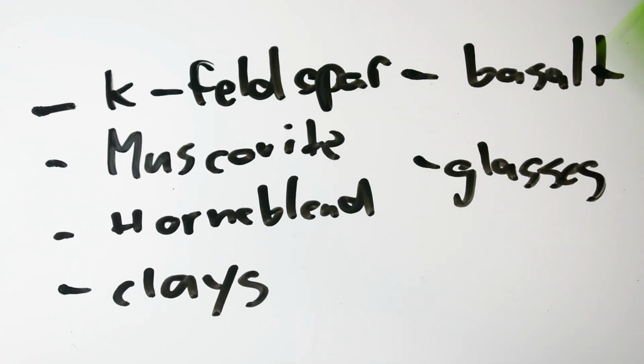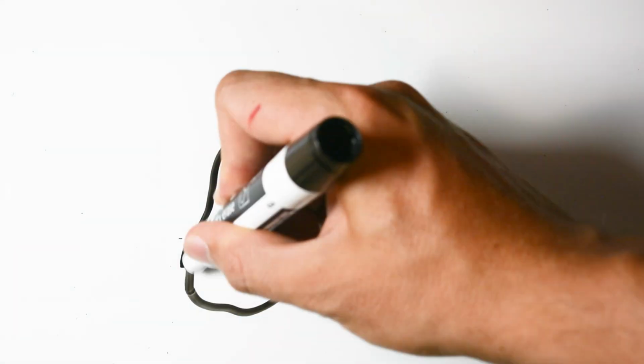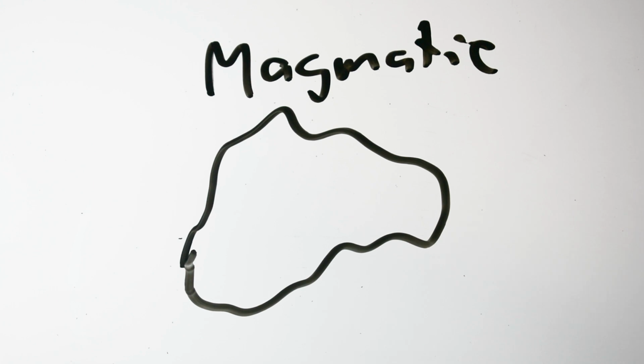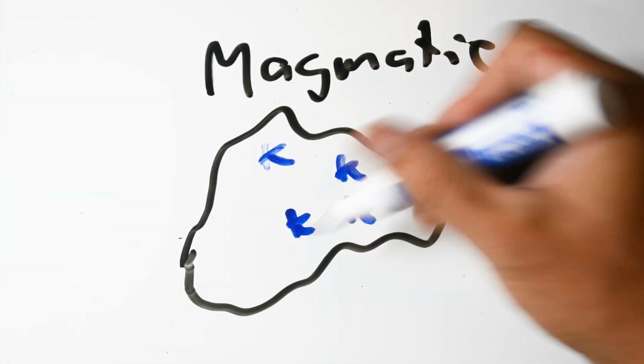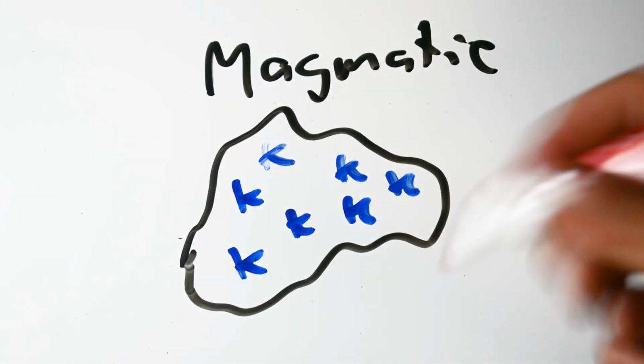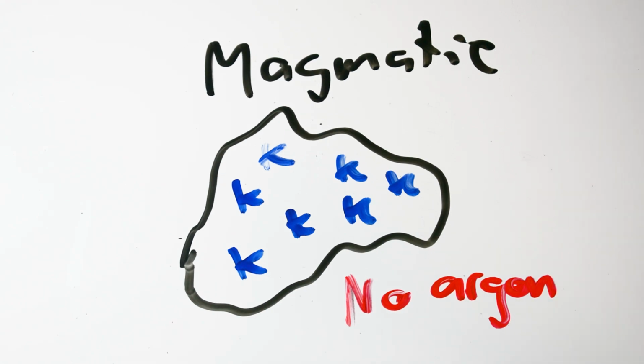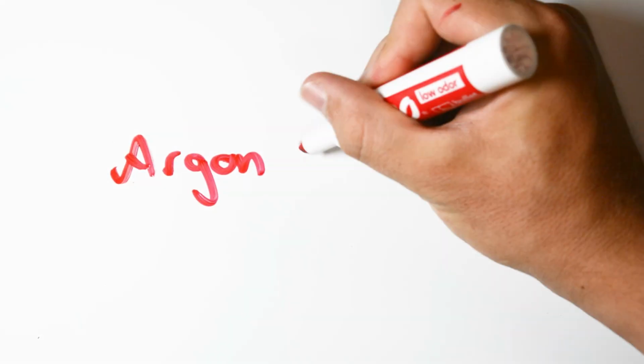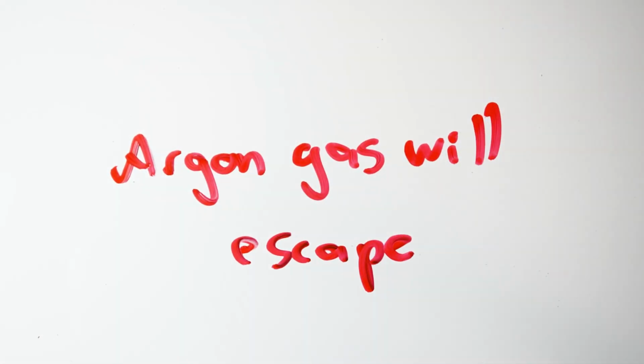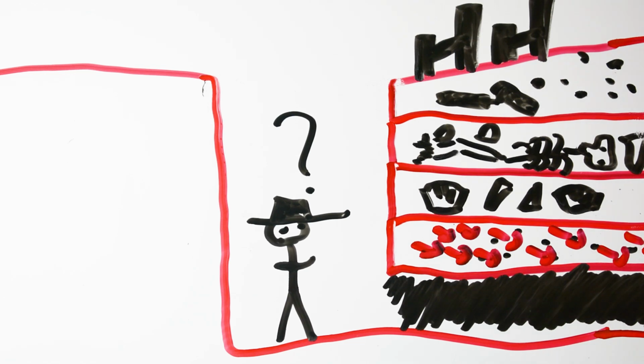As it turns out, magmatic minerals contain a lot of potassium-40 and no argon. And even if there is argon, since argon is a gas, as the volcanic material is launched into the air, all of the argon gas escapes, leaving potassium-rich material to spread across the landscape. This dating method is also the only way that tephra shards can be directly dated. Presented with a thick layer of volcanic ash and tephra, potassium-argon dating is the obvious choice for our desert archaeologist to use in his predicament.